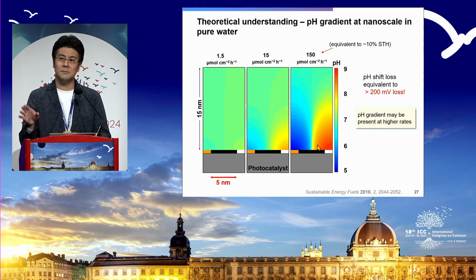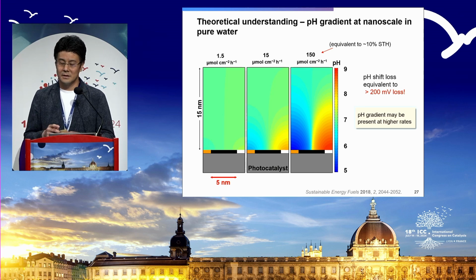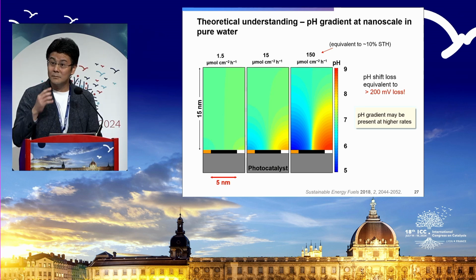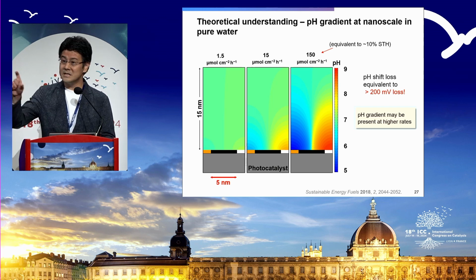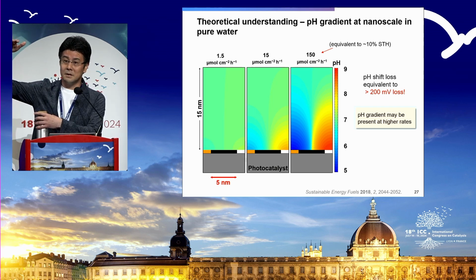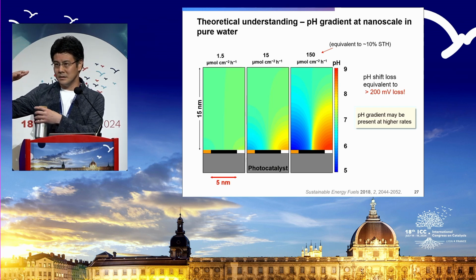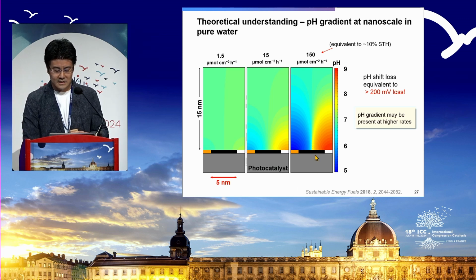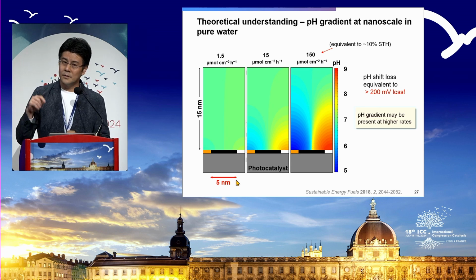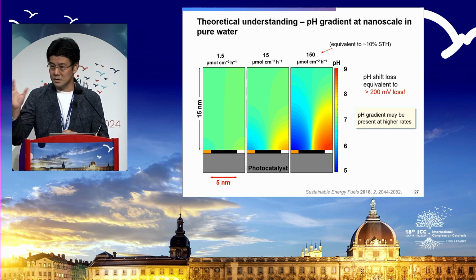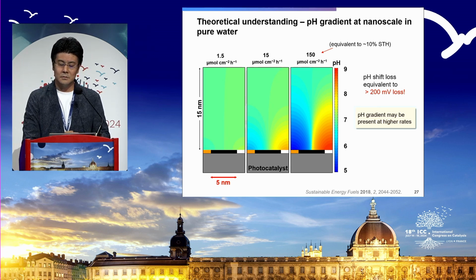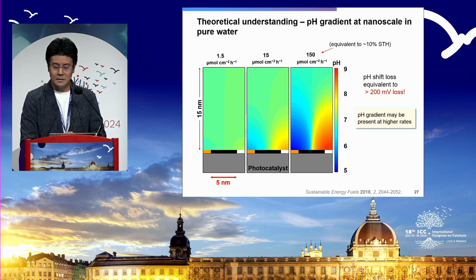pH 4 means 60 millivolt times 4. It's much greater than the 200 millivolt that is required for this pH gradient penalty. So this has to be added to the band gap, right? So this certainly has to be minimized. This is even at the 5 nanometer scale. Of course, from here, you need to give convection. You can stir it, or you can flow the water, to try to minimize the pH gradient. But I would say the pH gradient using pure water cannot be neglected.